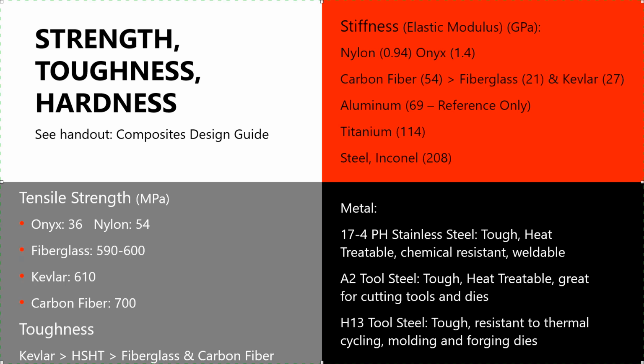So stiffness. If you're worried about stiffness and deflection, nylon's elastic modulus is about 1. ONYX is 1.4, so it's a decent amount stiffer. Carbon fiber is 54, ridiculously stiffer. So if you put carbon fiber into your ONYX material, it's going to be extraordinarily stiff. Looking at aluminum with a reference of 69 versus 54 for carbon fiber, you're probably going to be very close to the stiffness of aluminum, but with a density that's a third or less of aluminum. So really awesome strength to weight ratio. Fiberglass and Kevlar aren't nearly as stiff as carbon fiber, but they do help out a lot. And then titanium and steel obviously are much more stiff.